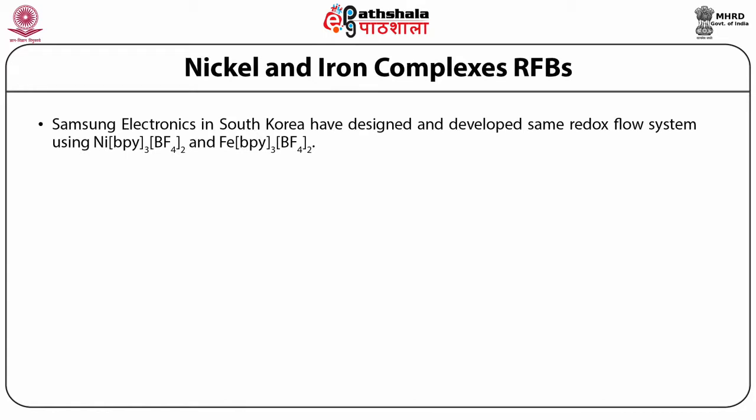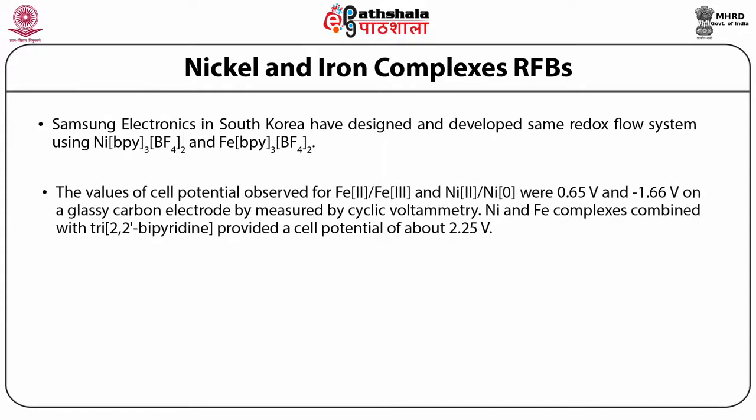Samsung Electronics in South Korea have designed and developed the same redox flow systems using Ni(bpy)3(BF4)2 and Fe(bpy)3(BF4)2. The values of cell potential observed for Fe2+/Fe3+ and Ni2+/Ni0 were 0.65 and minus 1.66 volts on a glassy carbon electrode, measured by cyclic voltammetry.